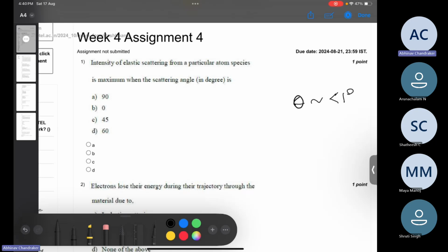Because nuclei occupy a very small space in the material, these elastic scattering phenomena are rare, and the scattering tends to be by very small angles. To help you visualize this, say an electron beam is coming toward a nucleus made of neutrons plus protons. This is a simplistic view. If the collision is head-on, you'd expect the scattering to be at a very high angle, almost backscattering.